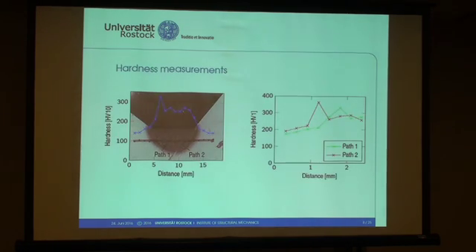Some hardness measurements here on the left-hand side. You can see the weld joint taken from one specimen, the weld metal in the middle, surrounded by the heat affected zone and the 2 plates here, the base material, and also the imprints of the hardness measurements. Here in the base material, there is a hardness of around 160, in the heat affected zone around 330, and here in the weld metal, it's around 250 or 260.